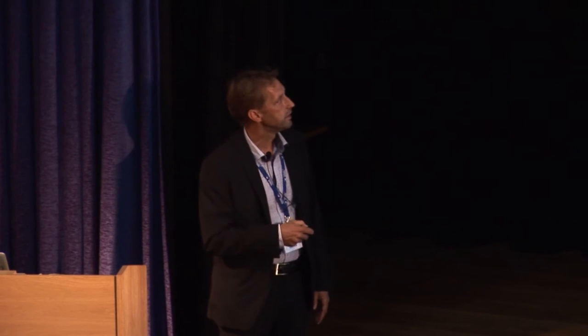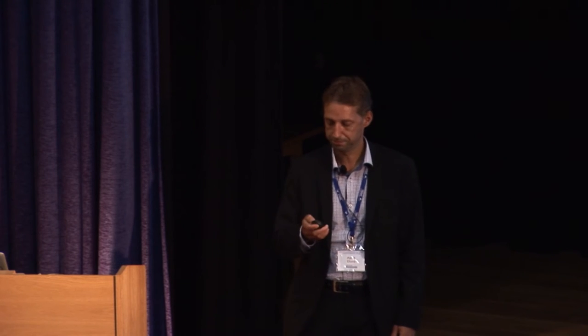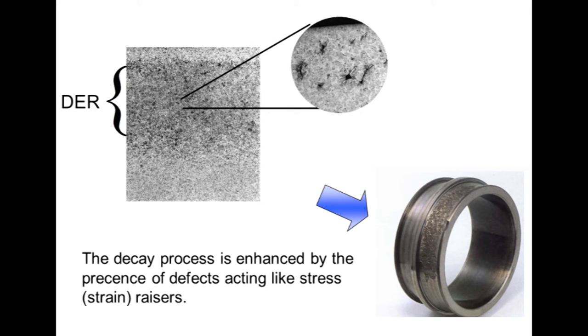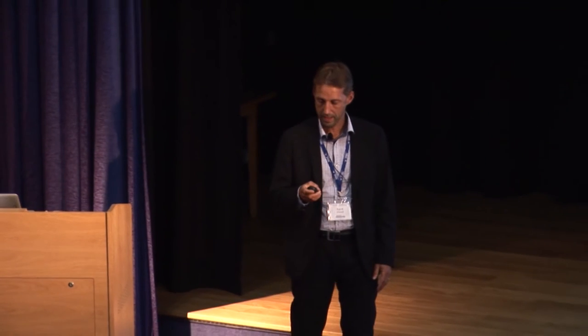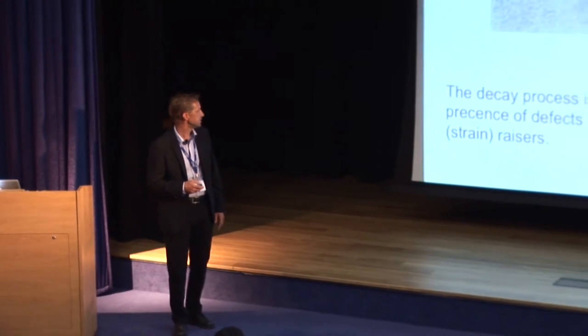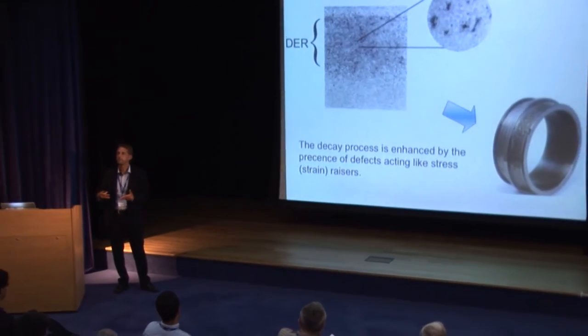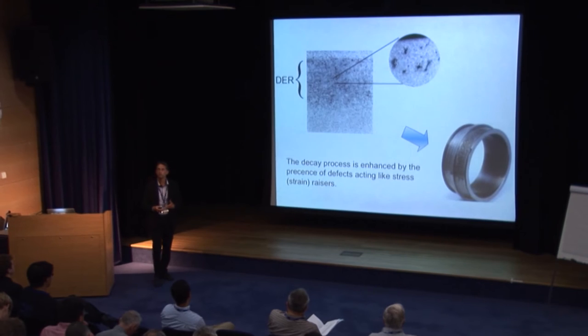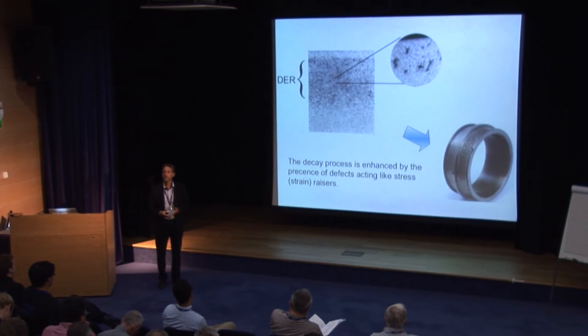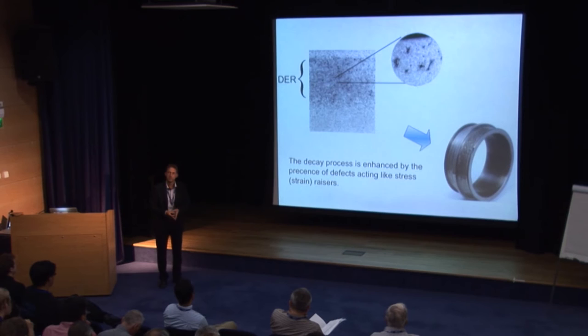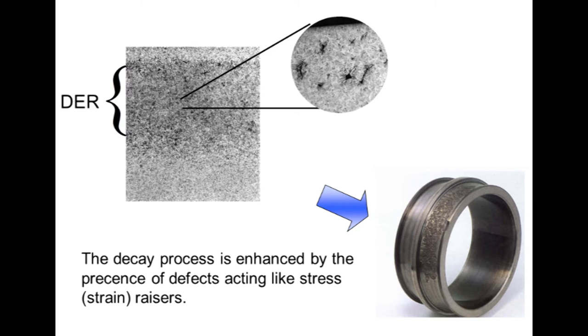And of course, then you're very interested in how different structures respond to this. Of course, we also have defects. And these will enhance this, because they are strain raisers, putting much more strain, putting more energy into the material, and promoting this material decay process. So this is the mechanism of fatigue that I think is extremely interesting, trying to understand this.